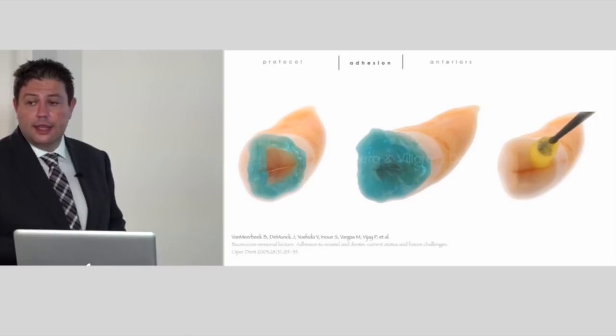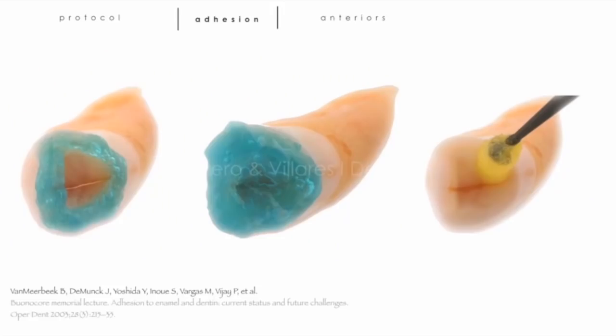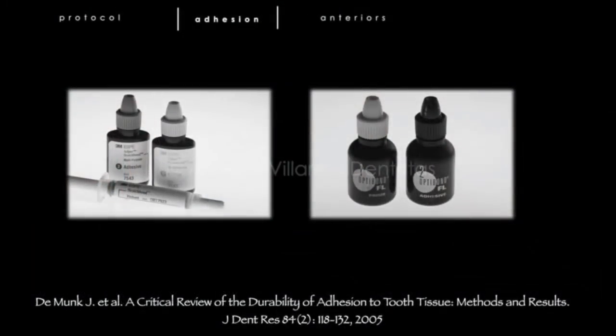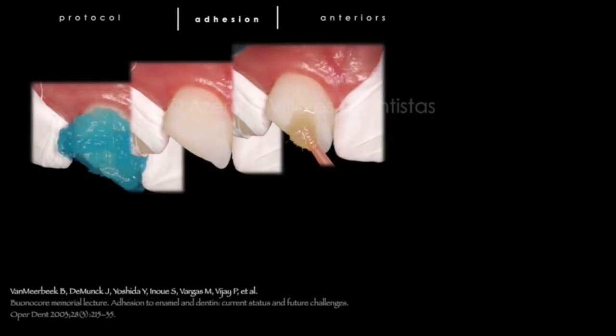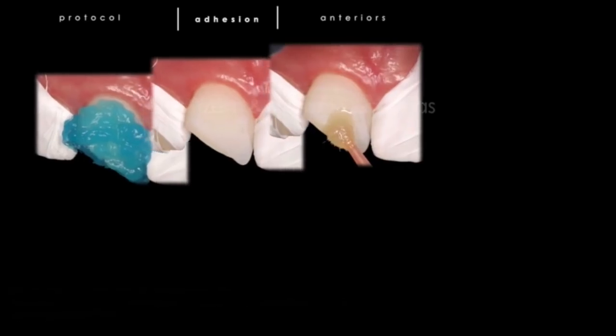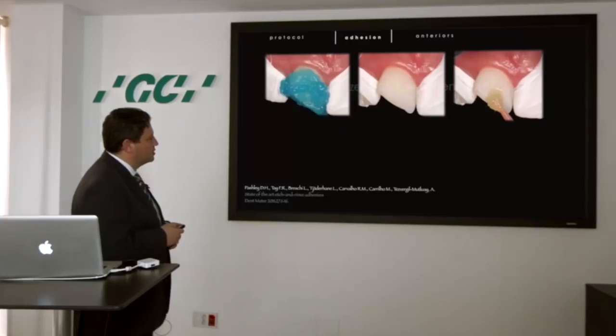About addition, nothing more to say than what we said before, but normally in anterior teeth what we do is the total etch technique, with etch and rinse adhesive. If we use 2 steps or 3 steps, the literature says that it's more important to use 3 steps, but I always say if you use 2 steps, do it in a proper way and you will have very good results. And normally the market and consumers are buying the two steps. So the most important thing is to know how to use your material. So use it, do it in a good way, and you will not have problems.